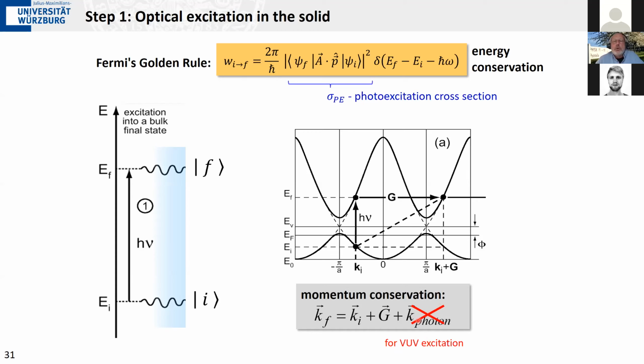As you go to higher photon energies, say in the order of a few thousand electron volts, that's called hard X-ray photoelectron spectroscopy, or HAXPES. You have to take this into account. It's no longer negligible, but it's just a constant that can be easily taken into account. And the other thing is this reciprocal lattice vector, and that's very neat, because in principle, you can map out several Brillouin zones here, and this can be done.